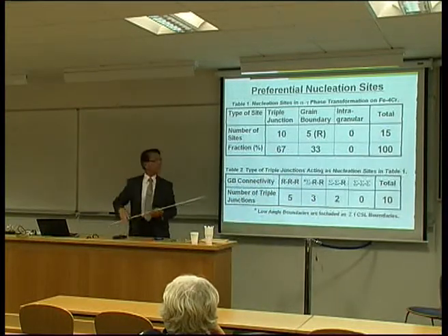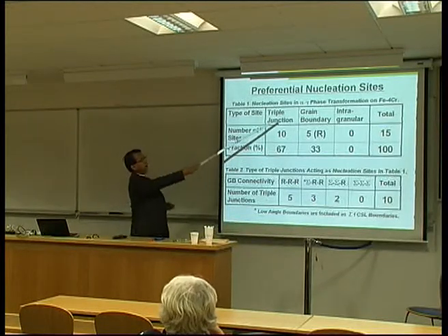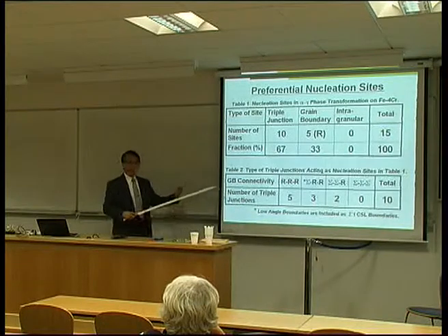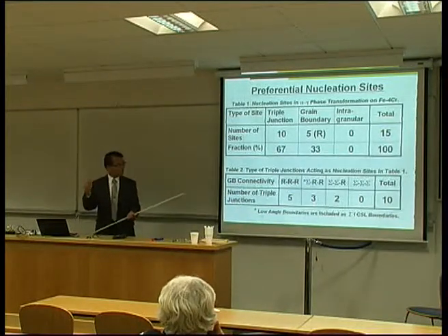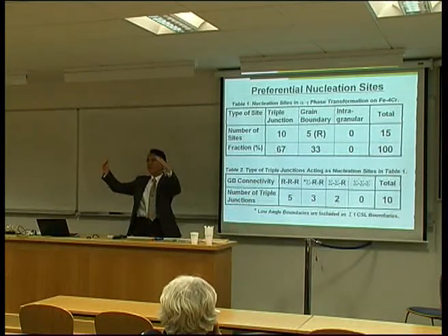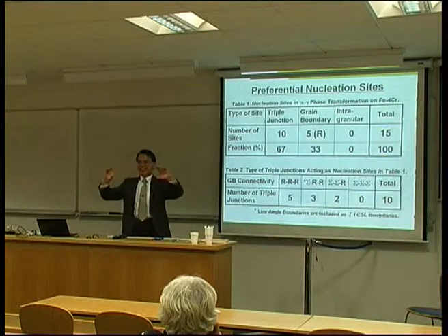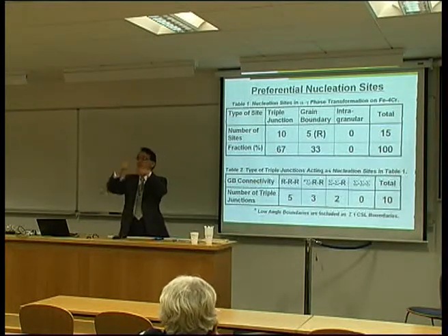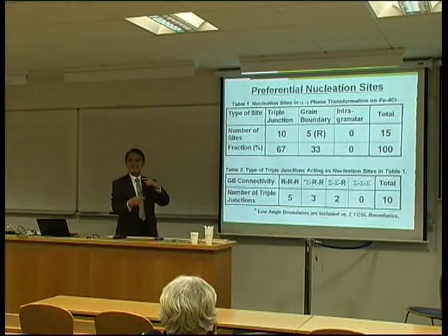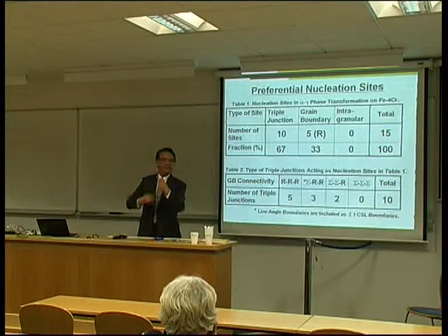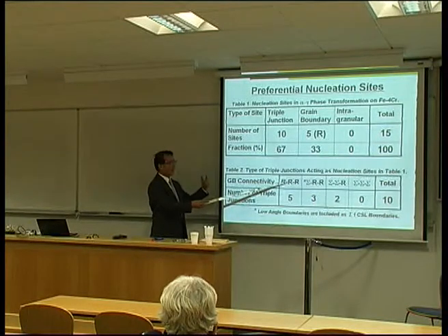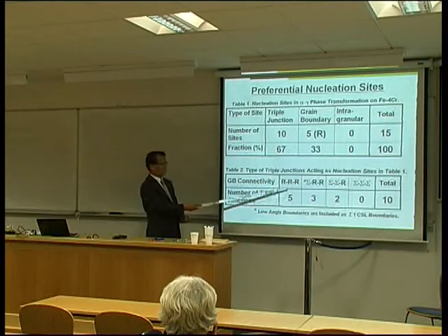So most of the gamma phase was formed at triple junctions and random boundaries. And what's the character of the triple junction which became a preferential site? As you see, a triple junction means three boundaries meet at a point or a line. In this case, as I mentioned, the individual boundaries have their own character. If we simply classify high energy random boundaries or low energy special boundaries like this, then if the triple junction is composed of three random high energy boundaries, this is the most preferential